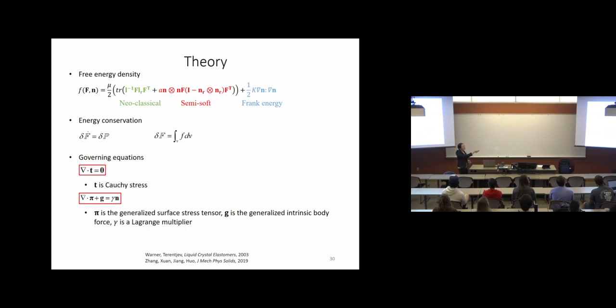We describe the free energy of the liquid crystal elastomer by the following components. First of all, the first term is this neo-classical model, mainly describing the liquid crystal behavior. Then the second term is called the semi-soft term, describing the non-ideality of the liquid crystal elastomer. The last term is the so-called Frank energy, describing the gradient of the director.